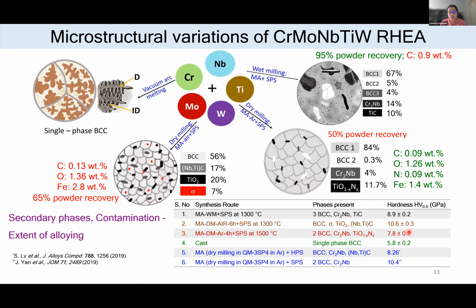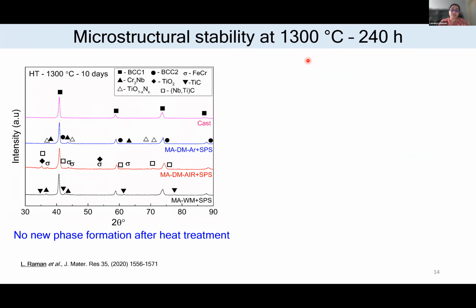So the table here shows some studies from the literature, apart from this work, wherein people have reported similar phase formation for this composition. So now that we have made this alloy, we have to really establish whether these alloys are thermally stable before we can actually study their properties. So for that, we tried to understand the structural stability at 1300 for 10 days. We vacuum sealed these samples in a quartz tube and did a heat treatment for a long time.